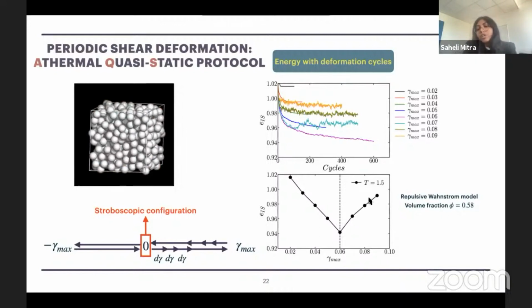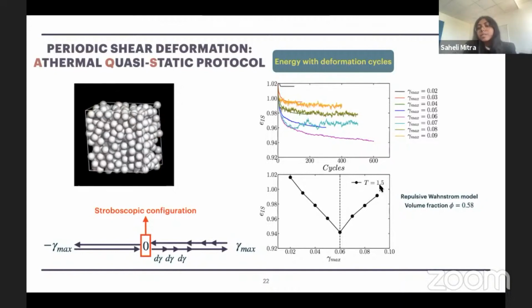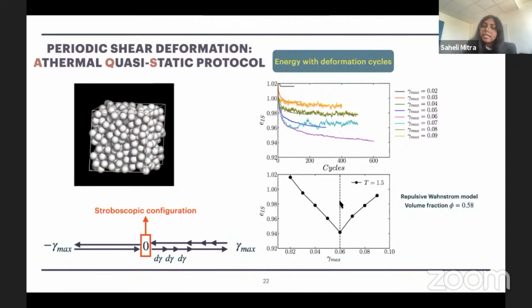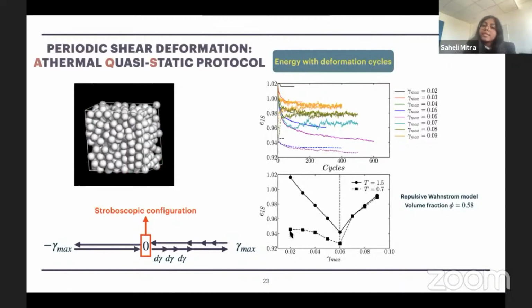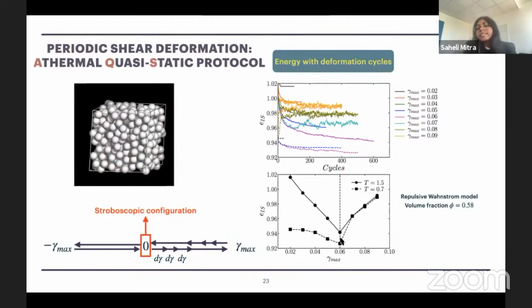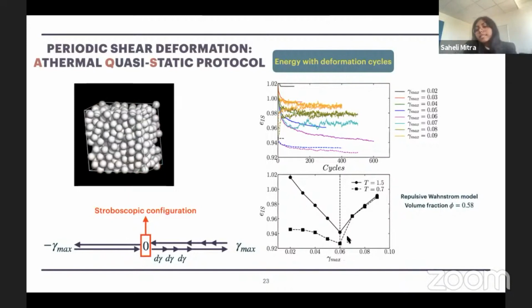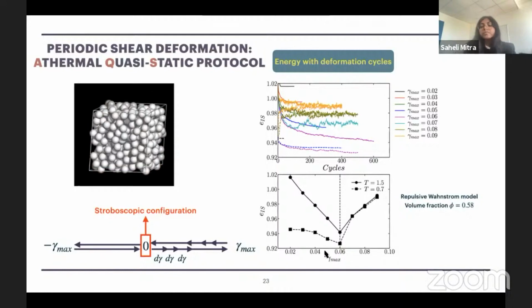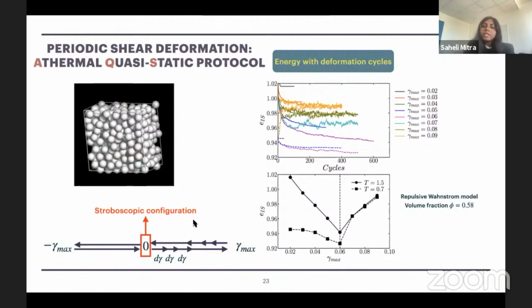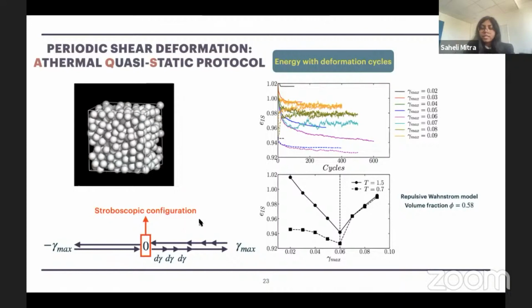Now, this happens for a system which was initially prepared at high temperature. If we repeat this analysis for a system prepared at lower temperature, we will see that this annealing effect is not that strong. And interestingly, no matter what their initial temperature was, upon crossing the yielding amplitude, the system reaches the same energy state.